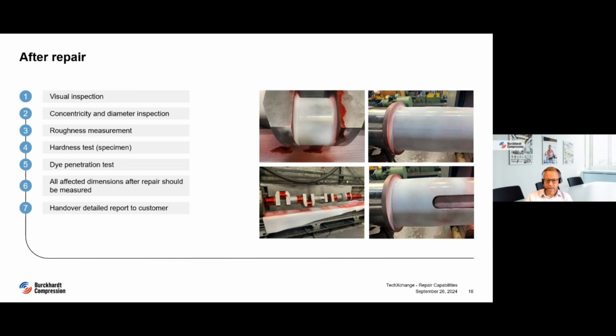Our last step before packing the crankshaft was our final inspection. We always perform the final inspection to be sure that all dimensions are within the tolerance and the surfaces are in a perfect condition. Also, the bluefit check of crankshaft to flywheel will be checked and documented. The final inspection consists of the following steps: visual inspection, concentricity and diameter inspection, roughness measurement, hardness test, dye penetration test. All affected dimensions after repair should be measured, and a detailed report with all carried out works is handed over to the customer. On the photos, you can see the final dye penetration test.